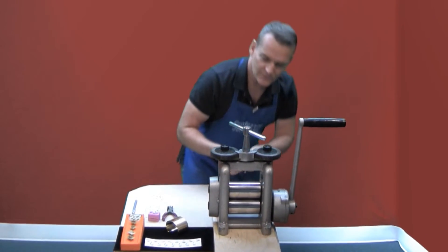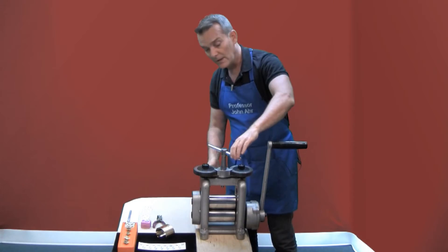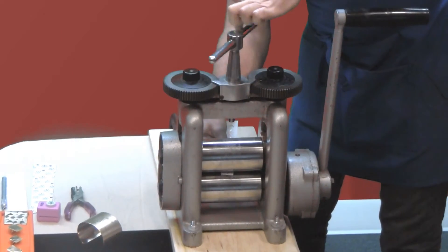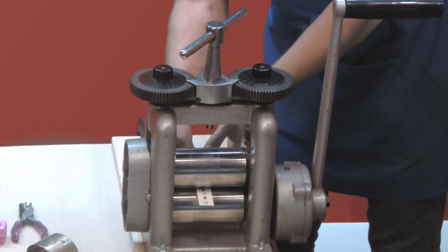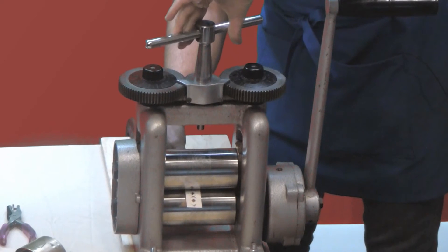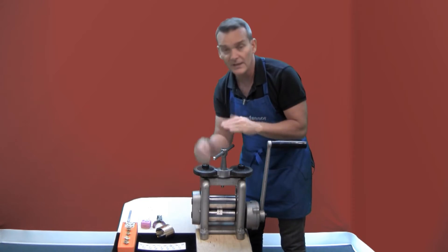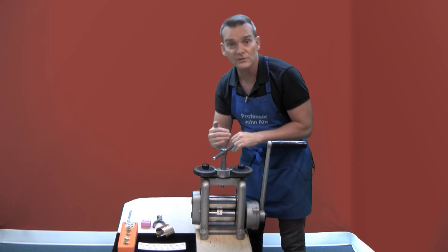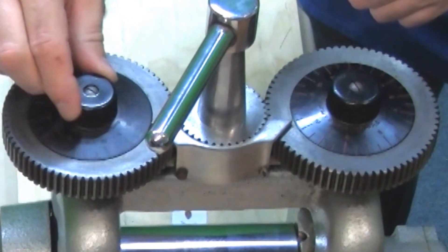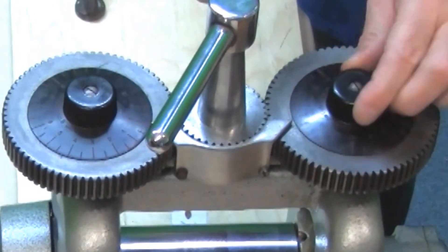The first thing I need to do is to open up the rollers of the rolling mill. I'm going to open them up just by cranking the handle and then put the material into the rollers. Next, I'm going to shut the rollers down and tighten them to the point where they give me a distance equivalent to the paper and the copper sheet. I'm going to use the dials at the top to record what that size is.